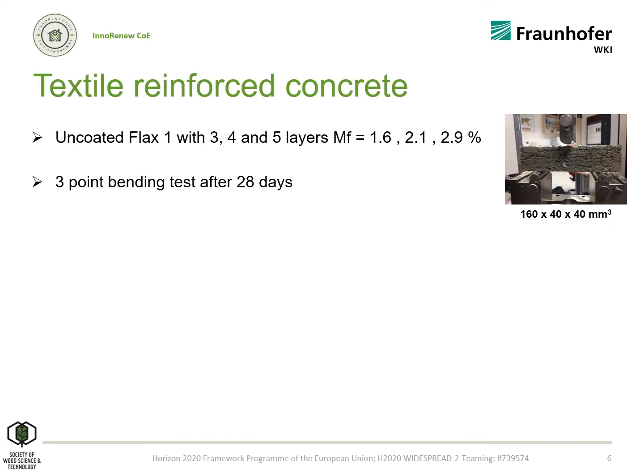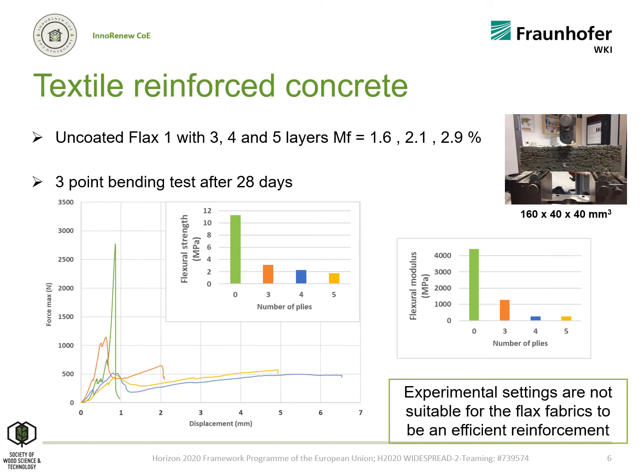We manufactured textile reinforced concrete with Flax 1 using 3 to 5 layers, and we tested them after 28 days by the 3-point bending test. The experimental results give the flexural strength and the flexural modulus higher for the plain concrete than for the concrete with flax fibers. So flax fibers here do not play their role as reinforcement.